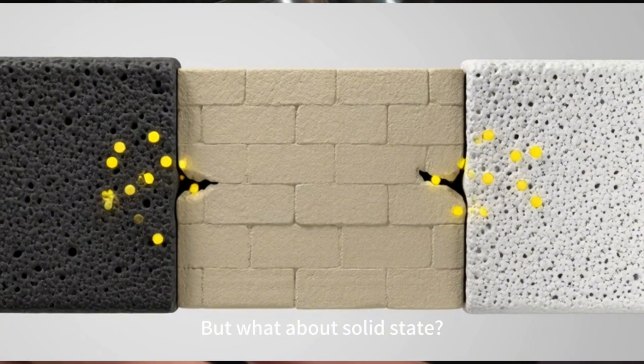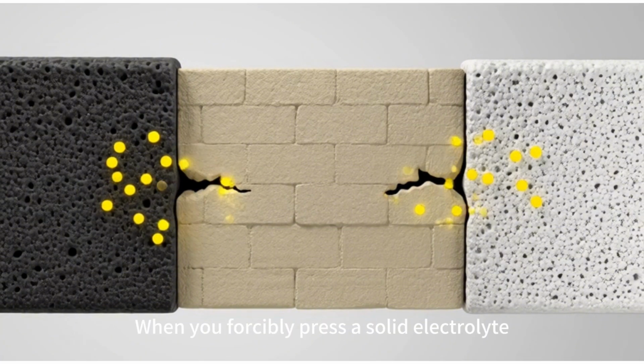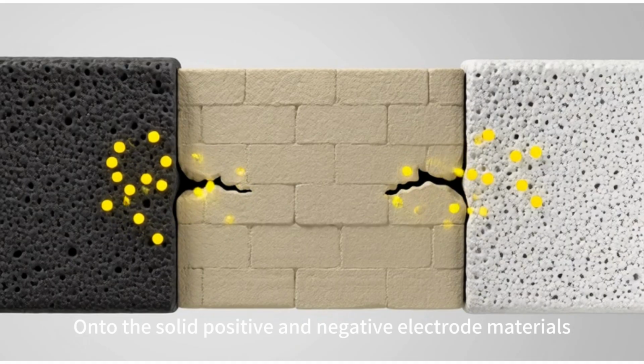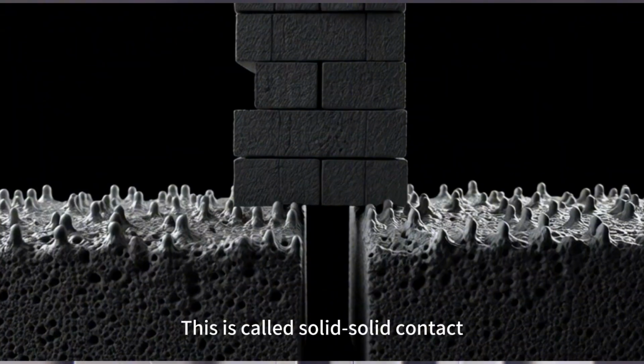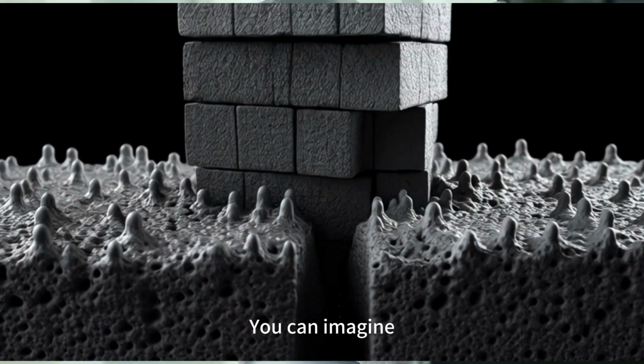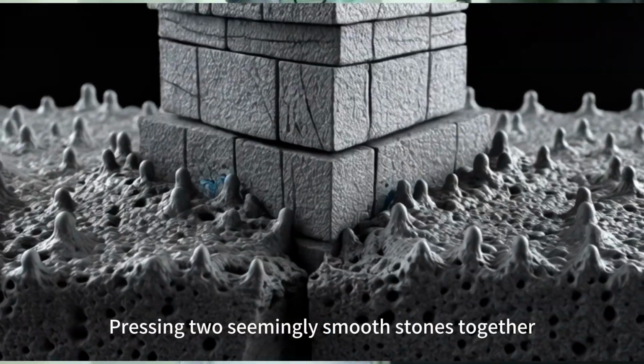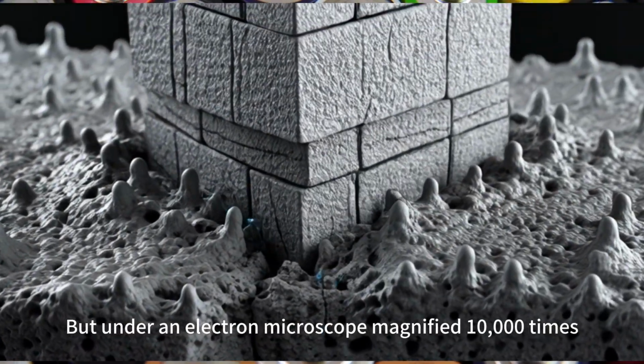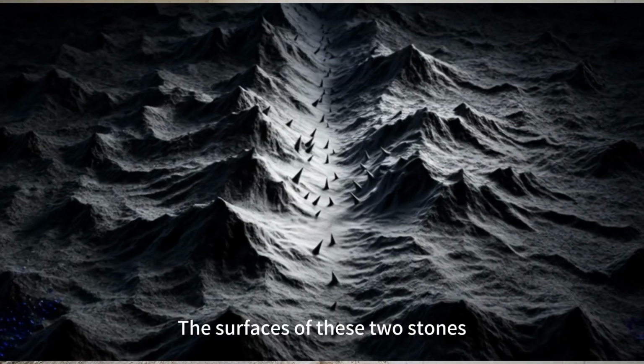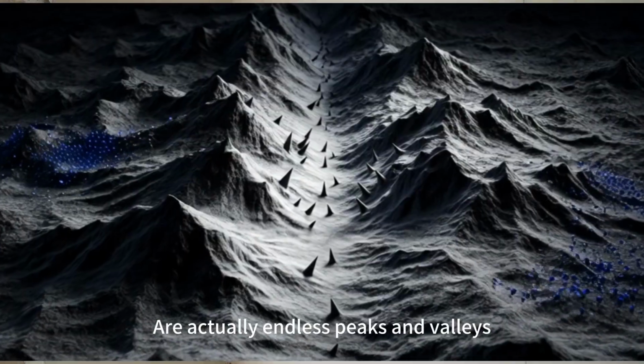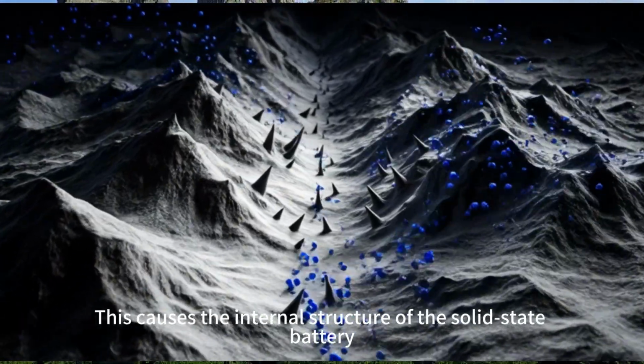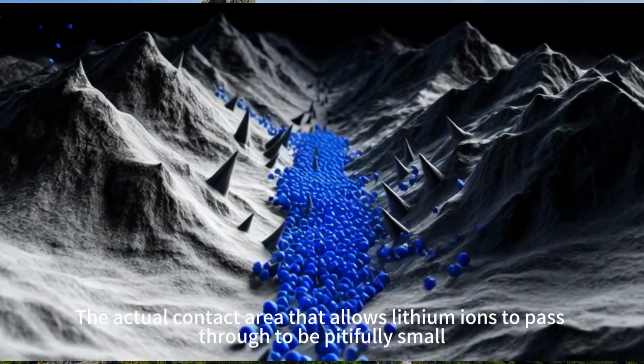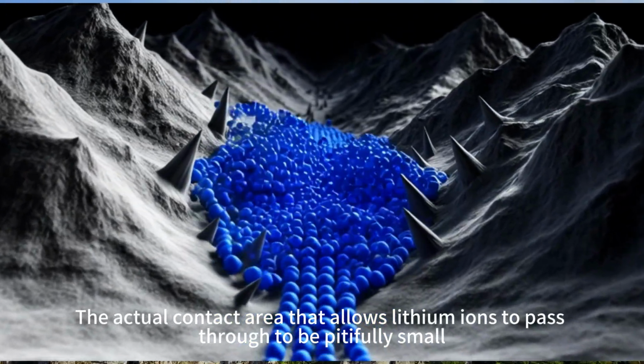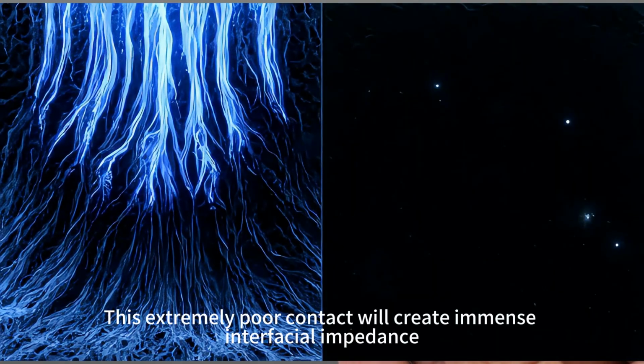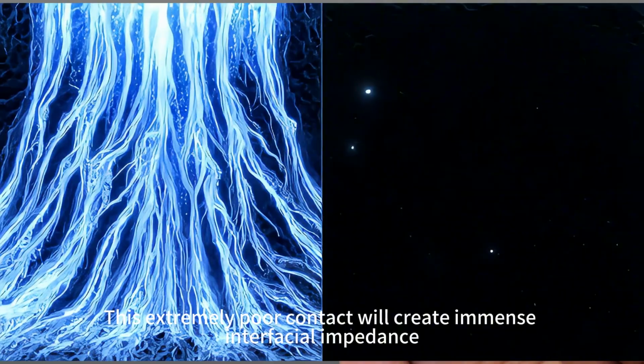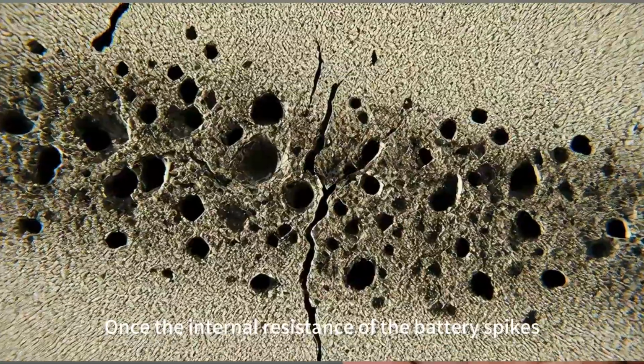But what about solid states? When you forcibly press a solid electrolyte onto the solid positive and negative electrode materials, this is called solid-solid contact. You can imagine pressing two seemingly smooth stones together, but under an electron microscope magnified 10,000 times, the surfaces of these two stones are actually endless peaks and valleys. This causes the actual contact area inside the solid-state battery that allows lithium ions to pass through to be pitifully small. This extremely poor contact will create immense interfacial impedance,